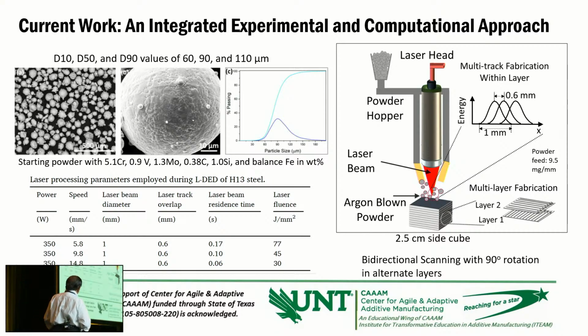Now, when you deposit the material layer by layer, if you move the laser in the same direction, what happens? The grains which grow from one layer into another layer will continuously grow epitaxially in an elongated fashion. If you cross-section this, if you move this beam in a linear fashion in the same direction, then the grains grown in the block or in the components will be very long, elongated grains, because the process is very rapid. Before the bottom layer cools down, the second layer gets deposited on it, and it starts growing epitaxially on top of the grains in the bottom layer, and you get a long elongated grain starting from the bottom layer to the top layer, and that is not a good situation.